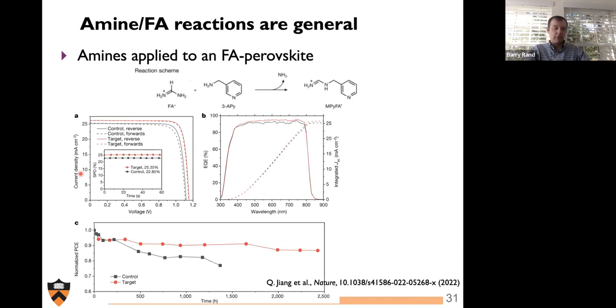Very recently, work from NREL, Ross and Kai and others, showed that you can actually apply amines to a formamidinium-based perovskite. Now, amines have been applied many times to methylammonium-based perovskites, whereby there is a proton exchange, and you can essentially replace surface methylammonium with some surface other ligand of your choice in this 3D, 2D stack approach. But this was an interesting work in that it was an early one, or the first one, to show that you can also apply this approach of a vapor phase amine to a formamidinium perovskite.